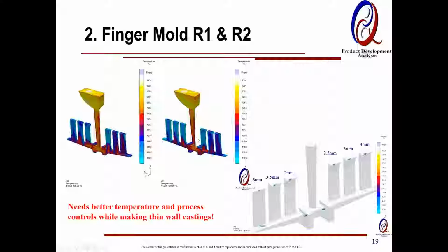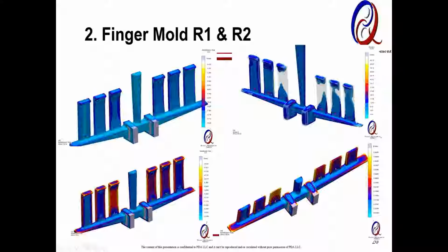So one thing we learned from a lot of this experimental work, with the support of university, Michigan Tech University helped us. They were part of the team on this. In order to make thin wall, you really need to have better temperature and process control because it's quite sensitive. Temperature of plus or minus 20 degree, what you see in the commercial environment, may give you a totally different result, and you may not succeed. So you need to tighten up your process controls.